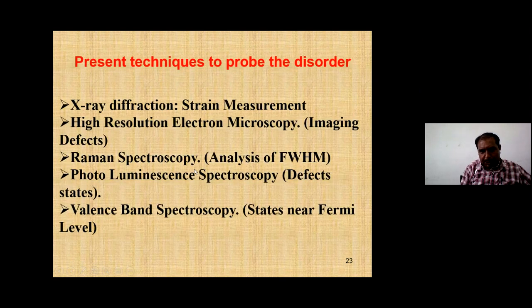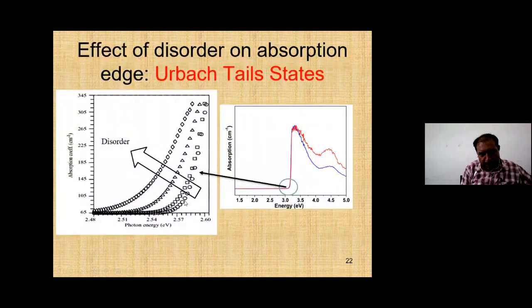When you have very small disorder present in the sample, the absorption is really very sharp, and when you increase the disorder, the rate at which the absorption falls is not sharp, but exponential, and the alpha of the exponential decay will change. From the value of alpha you can quantify the amount of disorder, which is essentially the electronic disorder resulting from defects present in your system. You can estimate it quantitatively using optical absorption spectroscopy, or using a simple reflectivity experiment.